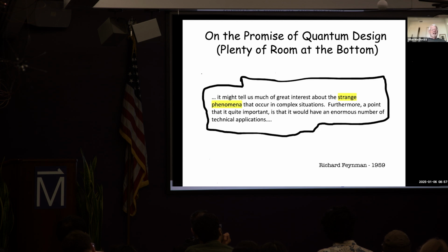So, in particular, moiré materials, it turns out, is a great way to make periodic systems, artificial crystals with lattice constants on the 10 nanometer or so scale. I'll say why that scale is important later. And we'd have actually even more flexibility if we could do that by lithography, and maybe eventually we will. But nowadays, moiré materials that I will talk about are the best way of making sufficiently perfect periodic structures on this 10 nanometer length scale that really act like crystals.